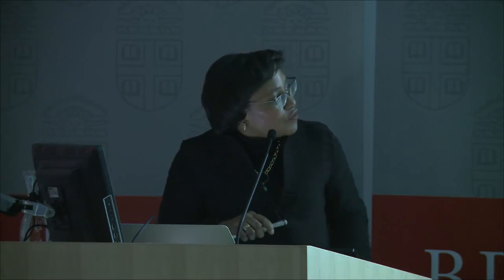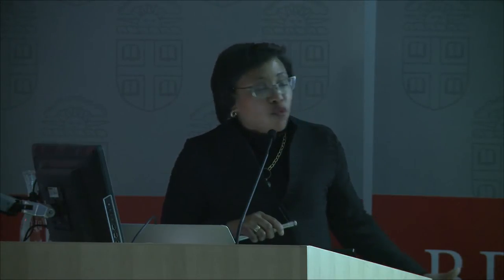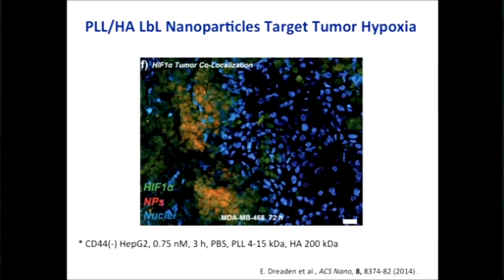And we can stain for hypoxia using HIF-1 alpha, which is expressed in hypoxic tumors. It's a green stain and nanoparticles in red, and we can see a direct overlap in the hypoxic regions. In this case of a tumor section, this is a histology section, indicating that we're getting a co-accumulation here. Okay, so we've got targeting based on size, we've got targeting based on hypoxia. Now we'd like to be able to also engage those receptors that are overexpressed on tumor cells.